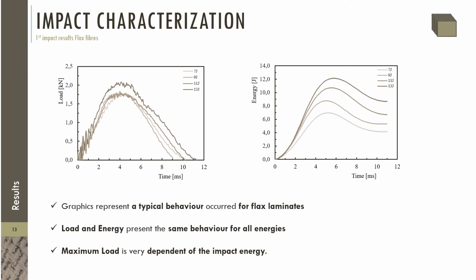In this slide, we can see the first impact results. The graphics represent a typical behavior occurred for flax laminates under different energies, and we can see that the load and energy present the same behavior for all energies. The load and energy increase up to a maximum value, followed by a drop after the peak load.